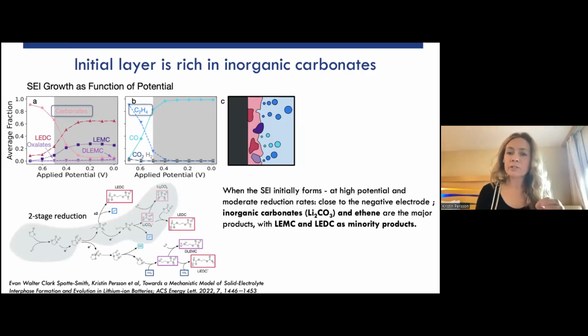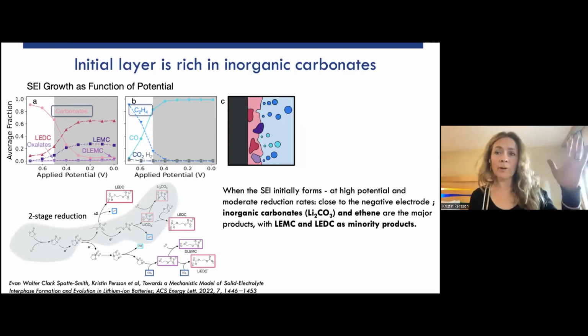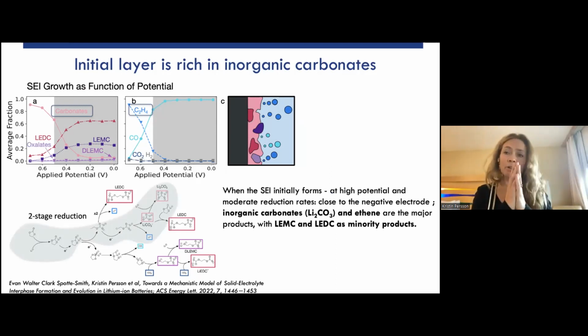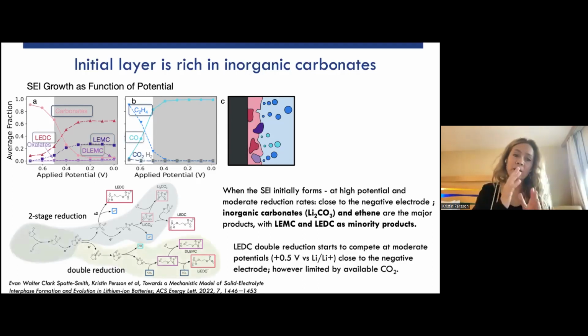The major products that we see at moderate reduction rates, close to the negative electrode, at high potential, are mostly inorganic carbonates. Lithium carbonate and ethene are your major products, with LEMC and LEDC as minority products. And again, LEMC is dependent on the amount of water. As you come down to about half a volt, you start seeing LEDC formation as a product close to the negative electrode. Again, this assumes that we have a very thin layer and not much of a barrier to electron tunneling.